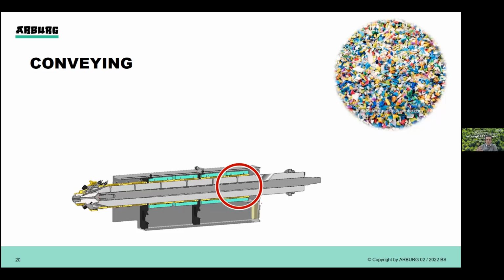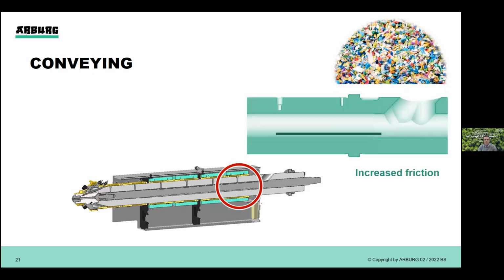But the conveying is also important and needs to be focused on. One step further towards solids handling: the regrind differs in grain shape and size, as mentioned before, so that the transport of these solids can be reduced. Therefore, the conveying of these solids can be improved by increasing the friction between the cylinder and the solid itself. This can be achieved by making grooves into the barrel, as shown on the picture by the dark green line. They prevent the material from circulating with the screw rotation, and help ensure that the material does not slip through.